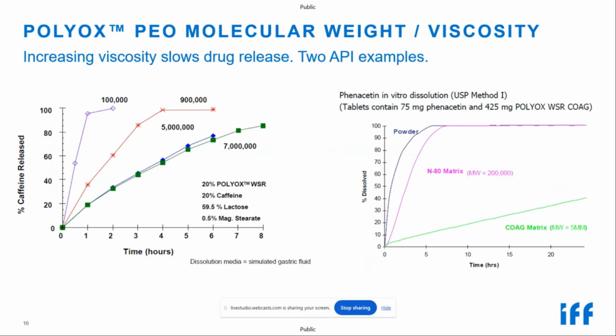The example on the left shows caffeine as a sparingly soluble model compound. The release is fastest with the low molecular weight, 100,000 Dalton, and it slows considerably with the two highest molecular weights of 5 million and 7 million Dalton, shown here in blue and green. The less soluble phenacetin on the right also shows a similar response to molecular weight, with a very fast release rate of the active using our low molecular weight N80, the 200,000 Dalton grade. And that release rate slows as you increase the molecular weight to Coagulant, which is 5 million. This is due to the very slow disintegration time that this grade has in water.